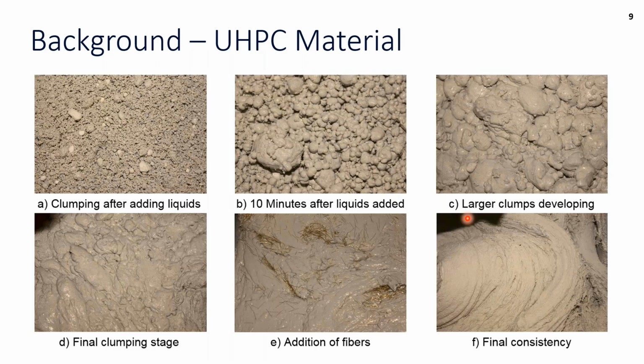Just a little background on the UHPC material, and I think this is just a great picture to show how different it is than concrete. If anyone has been on a project where you're working with UHPC or you've gotten a chance to touch it, mix it, it really is a different ball game, right? So it takes a while for the mix to turn over. And so if we have contractors that are not familiar with UHPC material, the answer can be like, oh, I think we need to add more water. It looks too dry. But this is the progression, and we see that different level of clumping. And then eventually, at the end, we're adding those fibers, and our final consistency is where we get that really nice flow. And that flowability is really important for the different ways that we can cast.